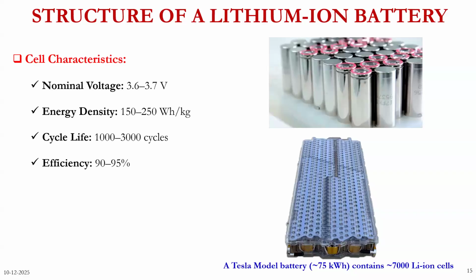So if the battery charge is 100%, it does not mean that your battery voltage is 3.6 volts. It means your battery voltage is a bit more than 3.6 volts, around 3.75 to 3.9 volts. I'm only talking about the mobile battery because it is very easy for us to see the state of charge there. Whenever you're using the mobile, the battery is getting discharged, and the state of charge slowly comes down to around 10% or 20%, or 0%. It does not mean your battery voltage is zero. A lot of people have some misconception here. No, the battery voltage is not 0 volts.